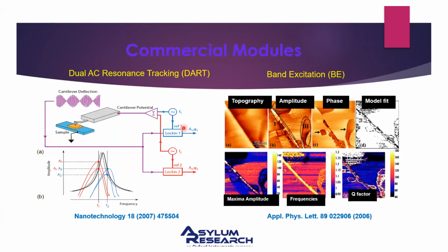To avoid these effects, some techniques were developed. One is the dual AC resonance tracking, DART. This is the most popular technique, and it is a commercial technique offered by Asylum Research. In this technique, you use two lock-in amplifiers to compare two frequencies and try to follow the movement of the resonance peak.